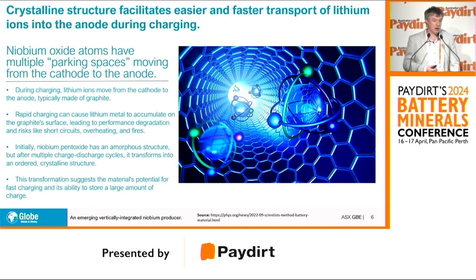during charging. So assume that in a battery without niobium, the atoms move from the cathode to the anode up the street, and there's only 1 parking space. But when you have niobium in it, there are multiple parking spaces from which it can select. And for that reason, it allows for the fast charging of batteries with niobium. Without niobium, the rapid charging can cause lithium-ion metal to accumulate on the graphite surface, leading to performance degradation and risk of fire and short circuit.